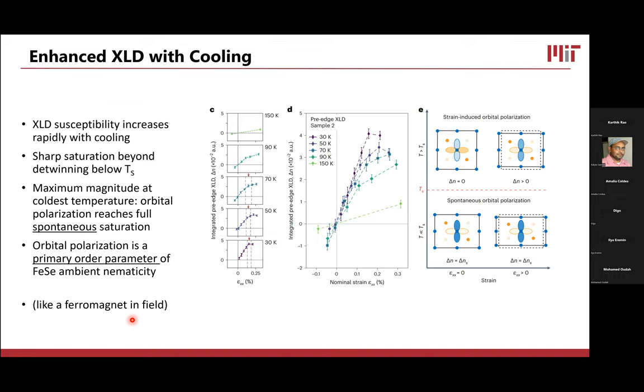Seeing this data was a very clear indicator for us that the orbital polarization is spontaneous and it is lattice independent. The changes that we're seeing with strain here are only coming from changing the domain population state. Before, if we're averaging over two different domains, the two effects cancel each other out. And once we fully detwin, we're only getting a signal from one domain. And then we get a large signal that increases as we go colder and it saturates at large strain. So that's essentially the key data for this story about orbital polarization.